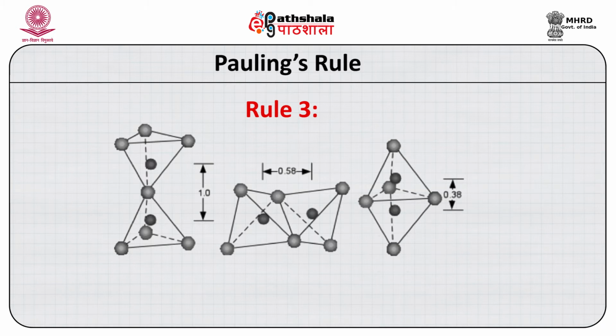For tetrahedral coordination in this figure, if the distance between the cations in the polyhedra that share corners is taken as 1, then sharing edges reduces the distance to 0.58. Thus, sharing of faces reduces the distance further to 0.38.